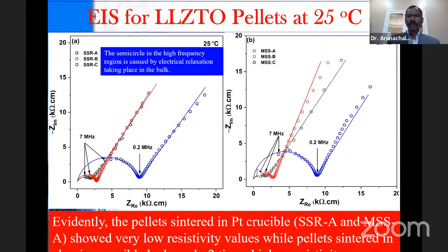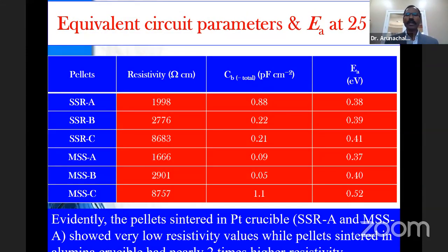You can see we also did a little bit of line fitting. The semicircle in the higher frequency region is mainly due to the relaxation taking place in the bulk. Certainly, the pellets sintered in platinum crucible showed lower resistivity compared to those in the alumina crucibles. Here we can see the parameters estimated from the impedance patterns: both the resistivity and the capacitance, that's the total, and activation energies. The pellets sintered in platinum crucible showed around 0.38 eV as activation energy.